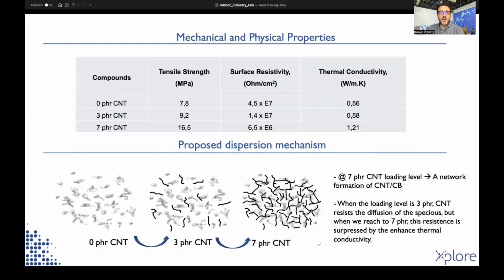As we look at the mechanical properties, although the cross-linking density dropped at 3 PHR carbon nanotube addition, we observed a slight increase in tensile strength, but an eye-catching jump at 7 PHR carbon nanotube.